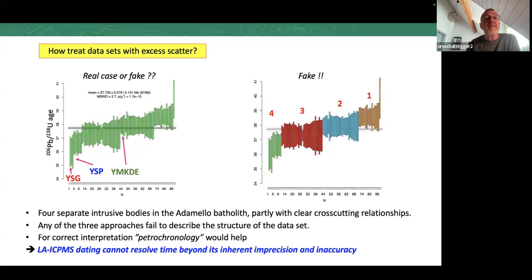So now I cheated a bit. This is not the real case. This is a fake case. These are 4 separate intrusive bodies in the Adamello batholith, partly, not all, but partly with clearly cross-cutting relationships. That means, in other words, that the laser ablation data we have assembled here completely fail to describe the structure of the data set.